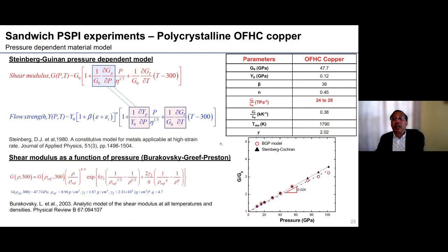So now we can start looking at the various material models. And so this is the pressure dependent model. Here, this is for the copper, the tungsten carbide model, which I have already shown. Here I show you the Steinberg-Guinan pressure dependent model. This is what we use for modeling the material. And so here the shear modulus is dependent on pressure. This is a well-known phenomenon, and it's also dependent on the temperature. And so these coefficients are given for the copper as described by the Steinberg-Guinan model. These constants are available in the literature, but I will discuss what we have found a little bit later.